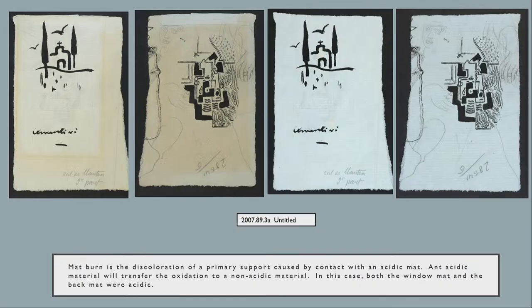Another Dalí example. Now, this is an interesting one. So we talked about foxing due to acidity. This discoloration, if you look at the first image on the left, you see a sort of outline on the perimeter and kind of whiter in the middle. This is a substrate which had an image on both the front and the back. And this was not iron gall ink, it's black carbon ink, very stable. This is what's called mat burn.